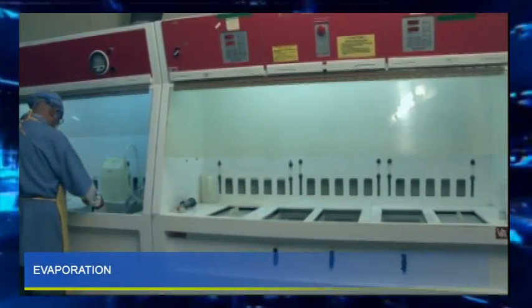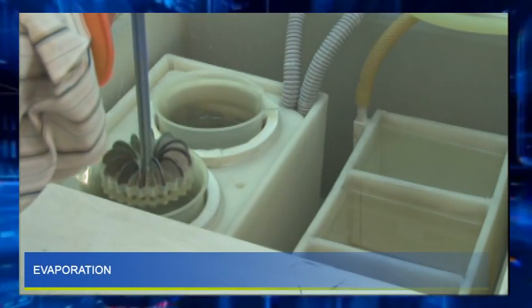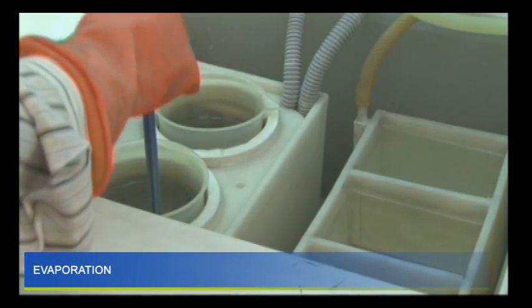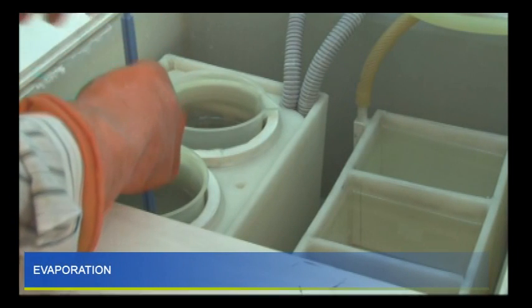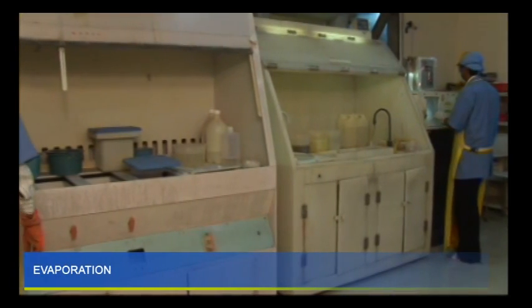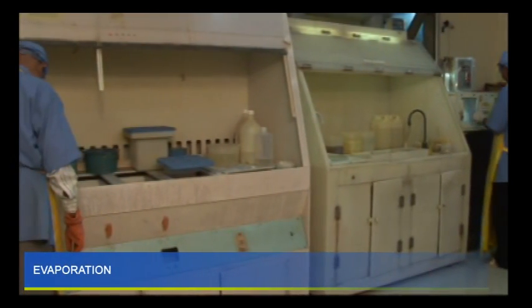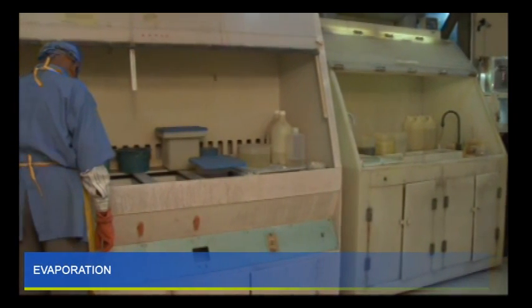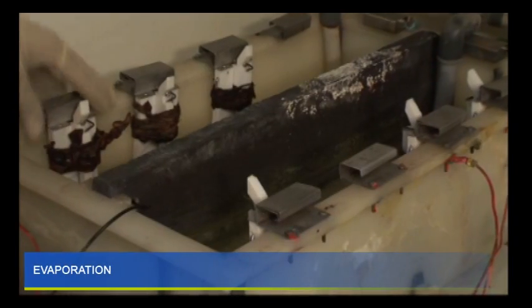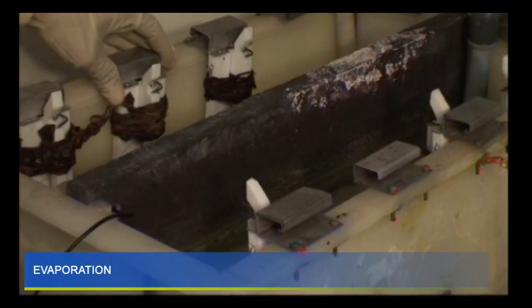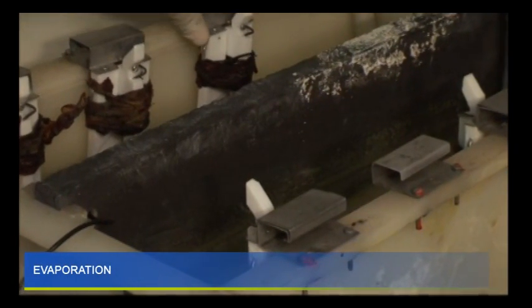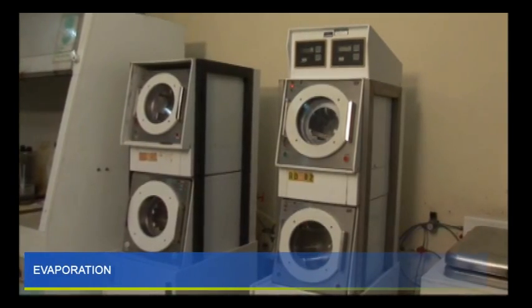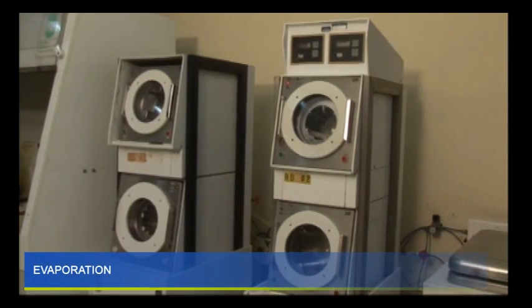In this process, the cathode side of the junction or the alloyed silicon chip is plated with 15 to 20 micrometer thickness of aluminium by the evaporation technique. The evaporation so done is by thin film technology. Substrates are loaded into the rotary planetary system inside the high vacuum chamber. The source aluminium is melted with the help of an electron beam power supply and it starts to evaporate and deposit on the substrate.